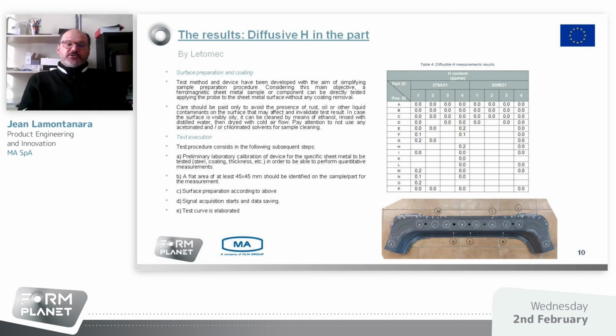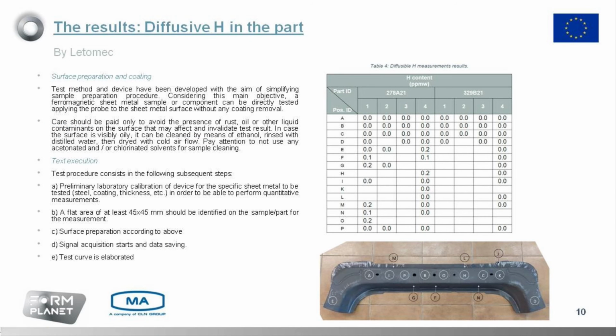So here we have the results. Some areas were measured for the diffusive hydrogen, and we can see that on all the samples measured by Letomec, we have some very low values in terms of diffusive hydrogen. A lot of points are at 0 or 0.1, or maximum is 0.2. So we are quite happy. It's not a surprise for us, this kind of results.